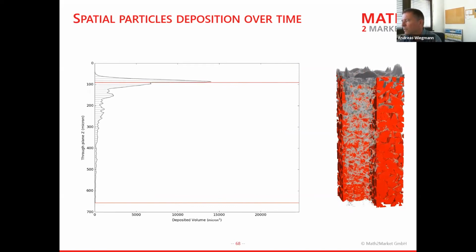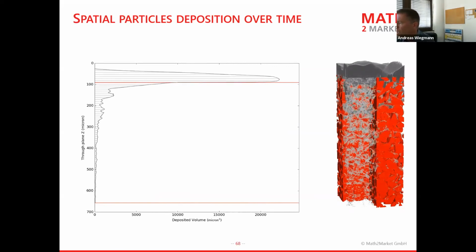On the right, we see a ceramic. We don't visualize the flow through there, but what you do see is soot being flown in from the top, and we see what's called filter cake growing on top of the ceramic. We also see the soot forming in the pores. There's a big cutout here, so we can see some of the soot inside the material as it is developing over time. I'll start the animation again.